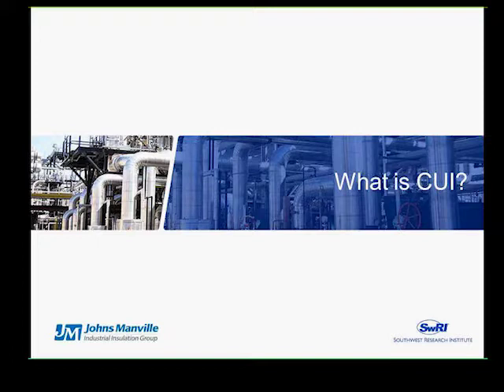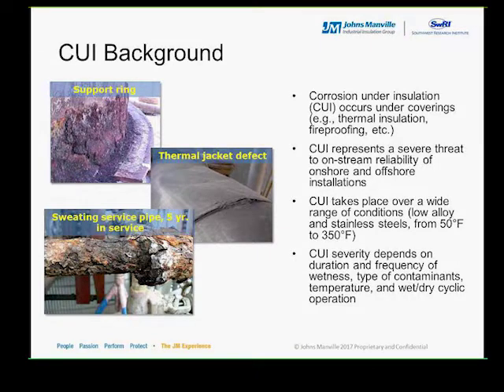Thanks, Ames. CUI background. Let me start by saying that corrosion under insulation, or CUI for simplicity, represents a severe threat to the on-stream reliability of many of today's refining, chemical, power generating, and pulp and paper industries, including onshore and offshore installations. In practice, CUI commonly appears in the temperature range between 50 degrees Fahrenheit and 350 degrees Fahrenheit, and where there's a cyclic operation of the equipment. For carbon steels, CUI manifests in the form of uniform and localized corrosion. For austenitic stainless steels, CUI is normally localized, leading to stress corrosion cracking if appropriate environmental conditions and stress levels are met. The effects of corrosion under insulation can be very severe. It can lead to sudden and catastrophic failure, especially in systems that operate at high temperatures and pressures.